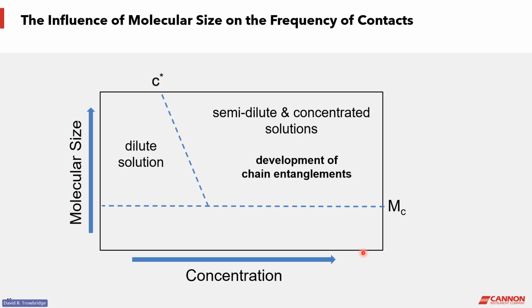Below this molecular weight, the polymer is not large enough to form significant entanglements. Above this line, if the molecular weight rises to this region, you can begin to form persistent chain entanglements. But below C star, as I mentioned on the previous slide, the molecules are isolated. And so they're not able to have the opportunity to make enough contacts to form entanglements. So down in the dilute region is where we don't have entanglements, even at the high molecular weights, where that could happen if the concentration was higher.